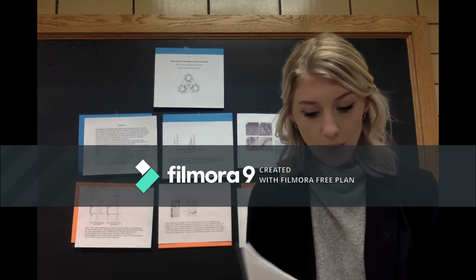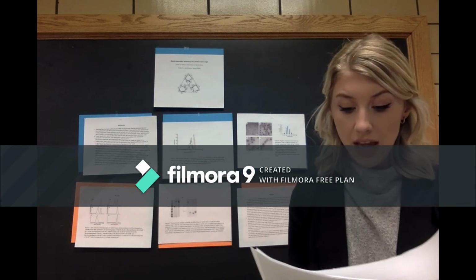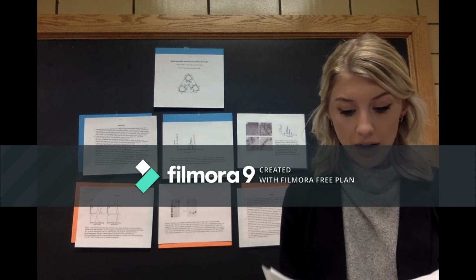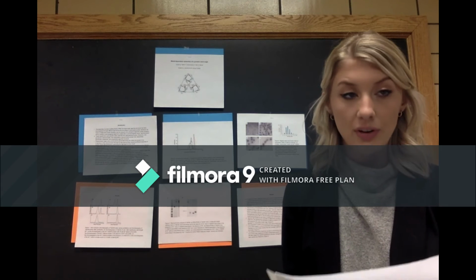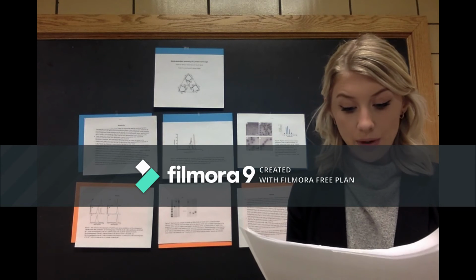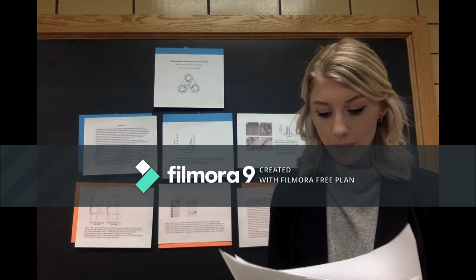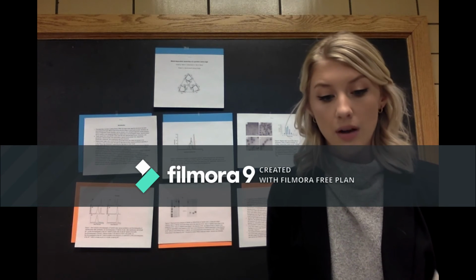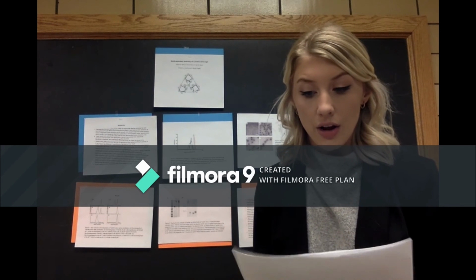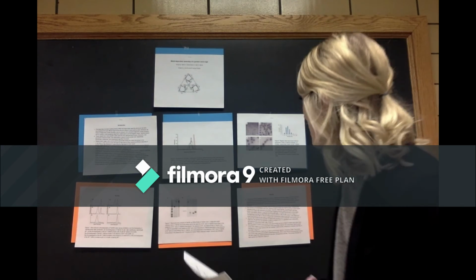The assemblies of TED8M were also studied using native PAGE to assess the homogeneity of protein assemblies, and the Ni-TED8M complex was cross-linked using the BS3 reagent prior to electrophoresis to prevent dissociation of the assembled material. The cross-linked TED8M sample migrated as a much larger species than the untreated TED8M sample, indicating nickel-mediated assembly of the protein. Control experiments confirmed that treating TED8M with BS3 in the absence of nickel 2+ ions did not cause cross-linking into higher molecular weight species, and that can be seen right here.